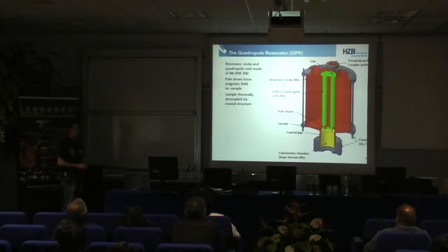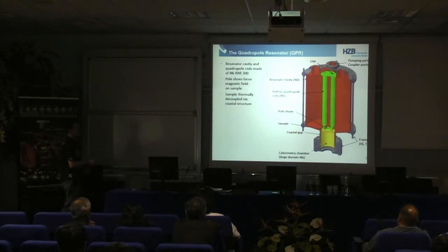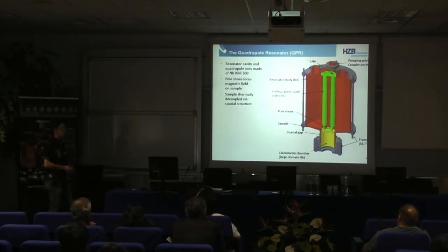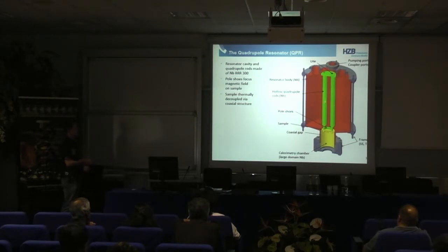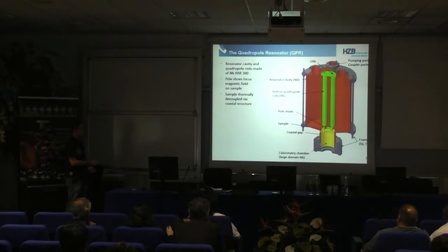I'll start a bit about what we have. You see in red a screening cavity out of niobium, and here in this cut two quadrupole rods connected with this pole shoe — this is a cut, so we have four quadrupole rods. These work as a transmission line and generate a quadrupole mode inside of this cavity. The whole system is put into a liquid helium bath cryostat and liquid helium is also filled inside of these rods, so these niobium rods are also cooled with liquid helium.